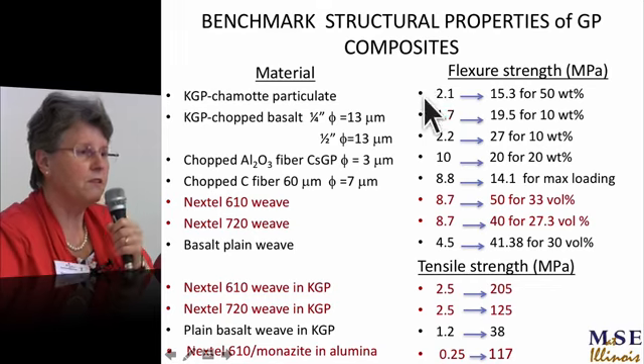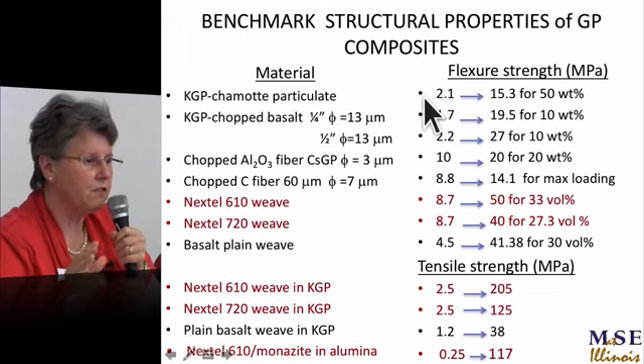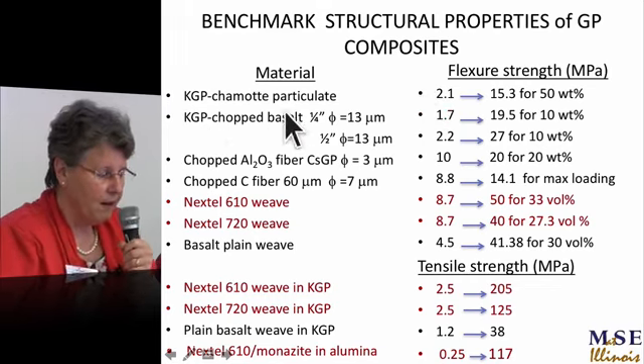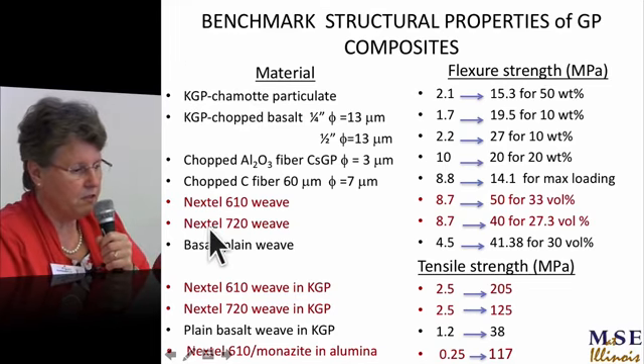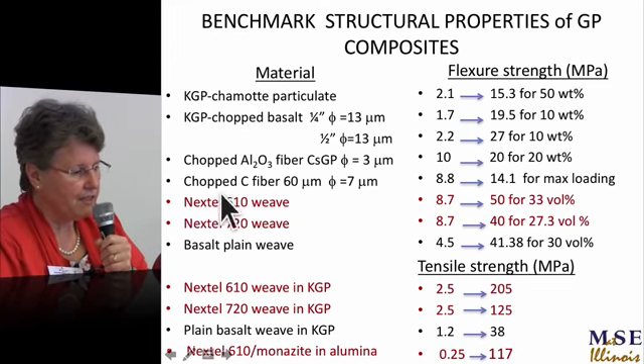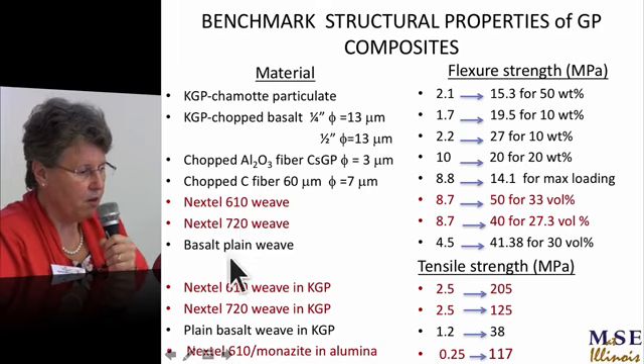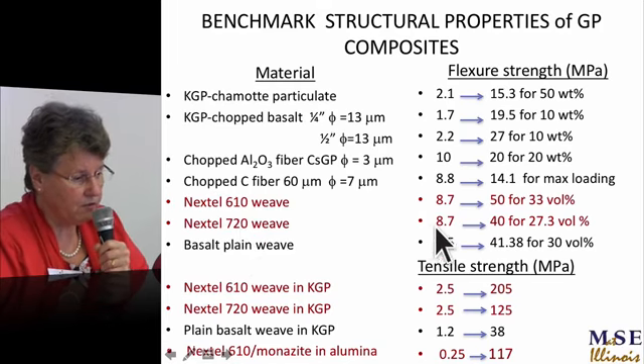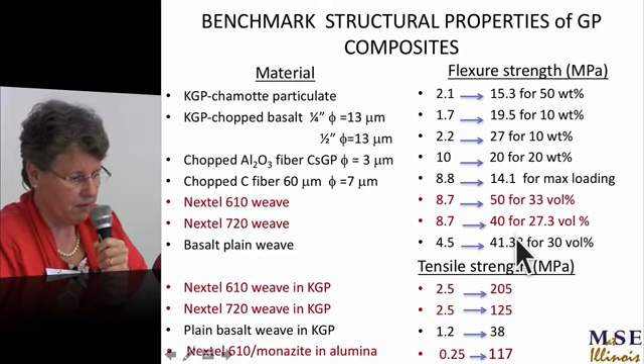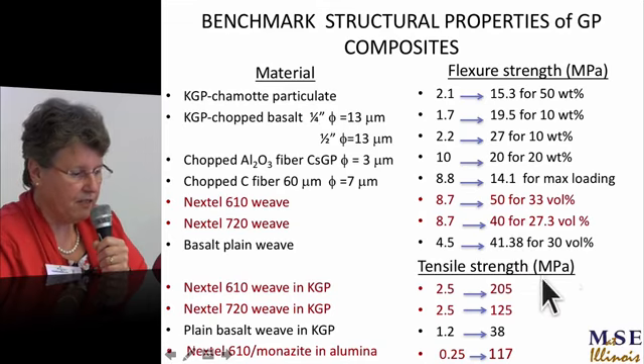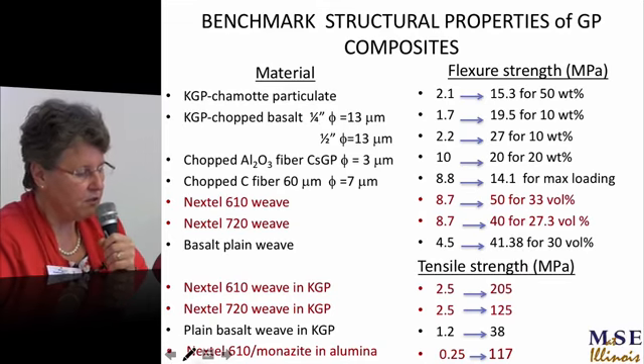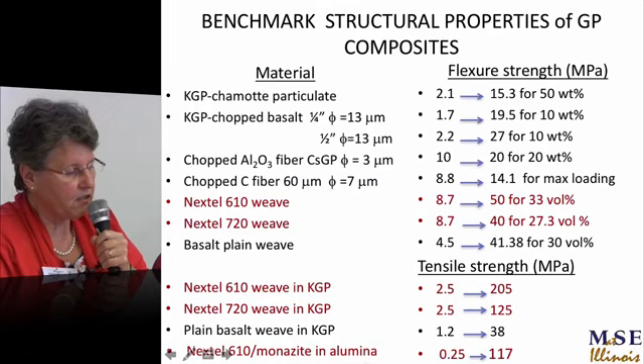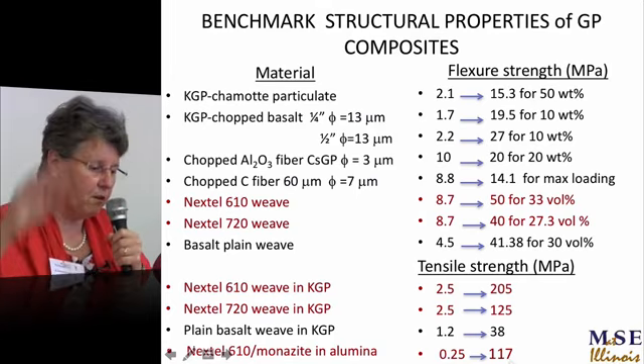Part of that was because the thermal expansion of cesium is approximately 0. So here's just a bit of a summary. Those particulates, the chopped fibres, and the weaves. The weaves have the best mechanical properties. The tensile strength: the best thing NASA uses now is Nextel 610 monazite-coated alumina fibres, and their tensile strength 117 at about 10 times the price.